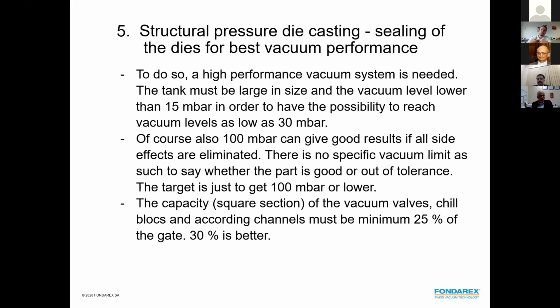The best vacuum level costs the die caster a lot of money. You have to seal everything perfectly. You have to have big tanks. Everything is slightly oversized. The target is just to get basically the air removed from the advancing alloy. If we can do that, we don't need 30 millibars. We can do it with 100. I have done better structural casting parts with 100 millibar than in some cases with 30 millibar, because 30 millibar also has much higher side effects.